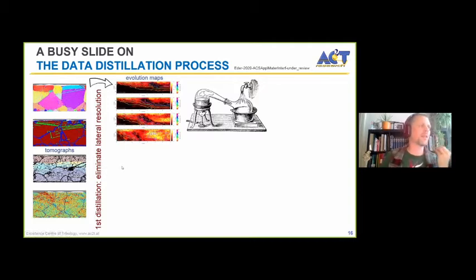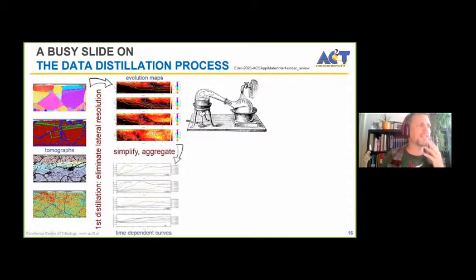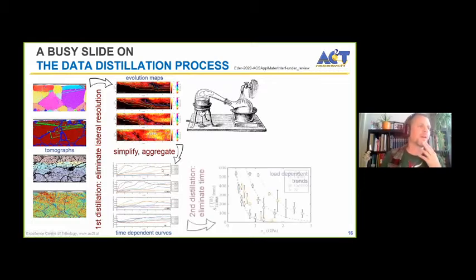So first we eliminate the lateral resolution of our system, and we produce these maps where we have time on the horizontal axis and the sample depth on the vertical axis. And then we can put quantities like the stress in shear direction, as seen here in the heat map, or these lines here represent the twinning activity in the sample over time. And this is for 4 different loads. And as we simplify that a little bit, we get one quantity of interest that we track over time. So we have time-dependent curves of some quantity that we're interested in, in this case, the formation of twins.